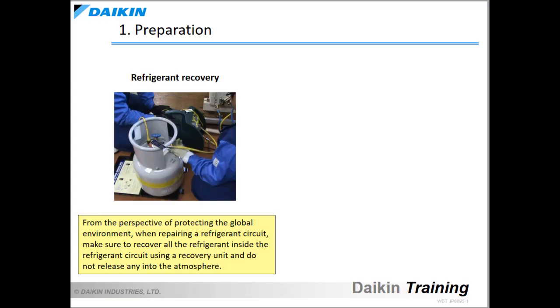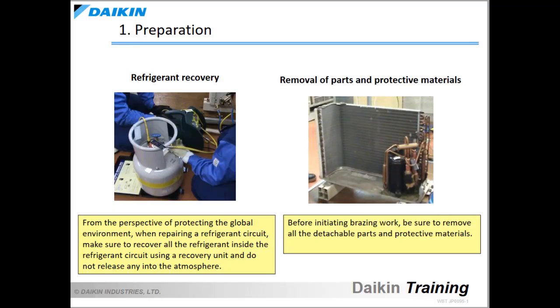If refrigerant piping is heated with a brazing flame while refrigerant is still inside the refrigerant circuit, it creates a risk that the pressure in the refrigerant circuit will increase due to the heat, causing the piping to burst. This can also cause refrigerant to be released into the atmosphere, which should be avoided from the perspective of protecting the global environment. Be sure to use a recovery unit in order to completely recover the refrigerant inside the piping before repairing a refrigerant circuit. In addition, remove any detachable parts and protective materials before initiating brazing work.